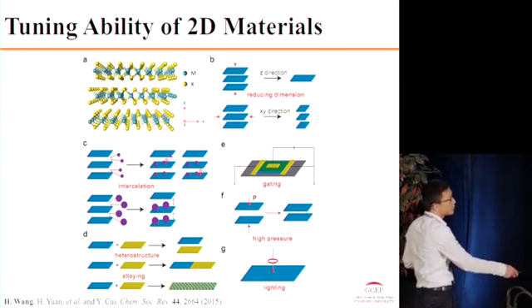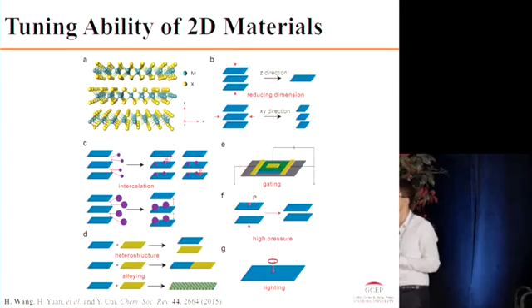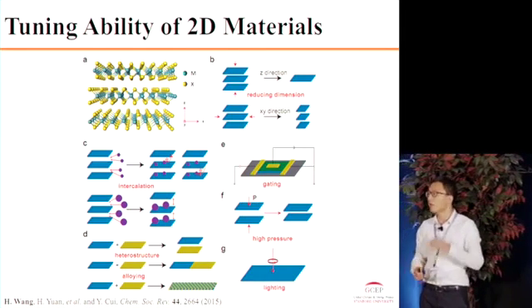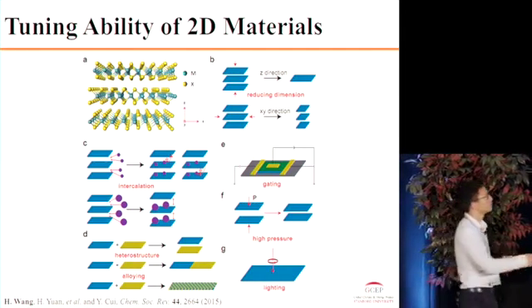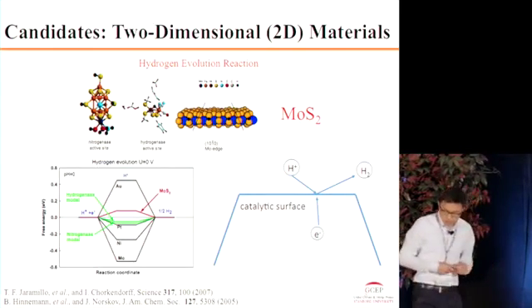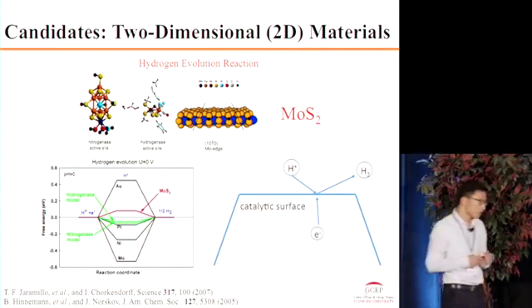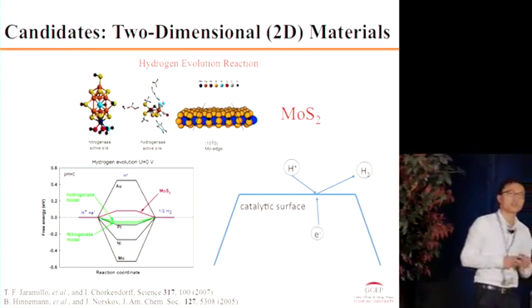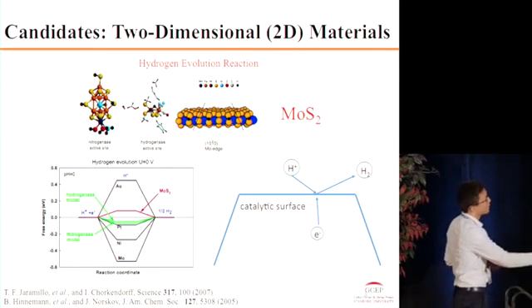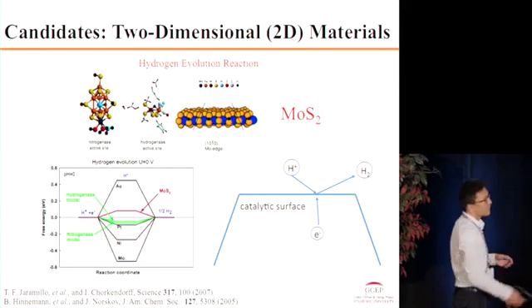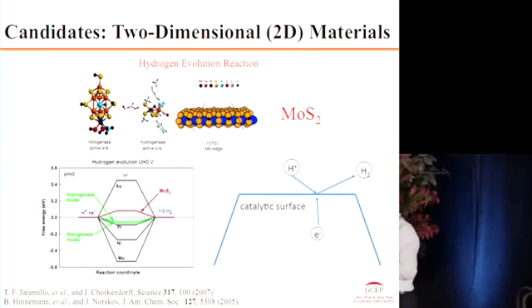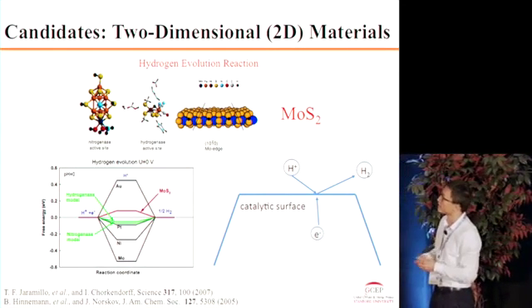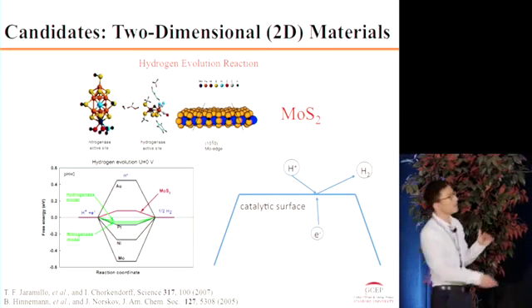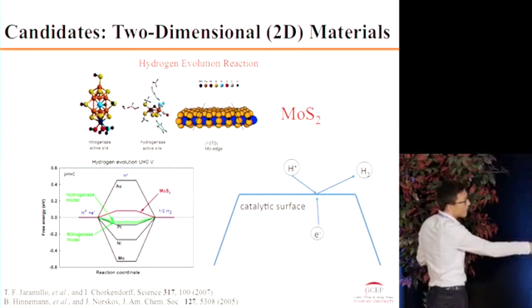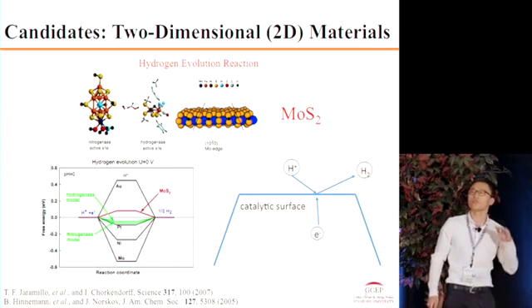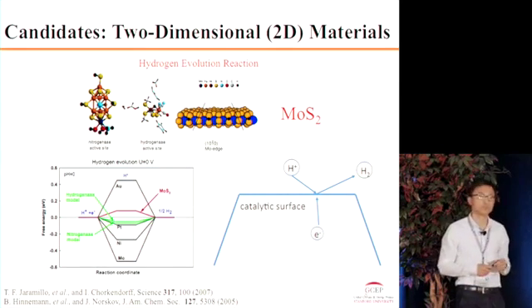You can do gating, you can do high pressure, a lot of different technologies for us to tune the material properties and also examine their catalytic activities. So molybdenum disulfide is a very famous, outstanding layered material, and it has been realized that the edge, in 2005, Professor Jens Nørskov actually predicted that the edge side of molybdenum disulfide, not the terrace side, but the edge side, is actually very catalytically active for the hydrogen evolution reaction.